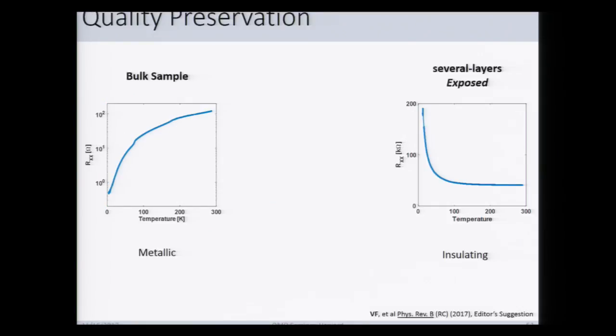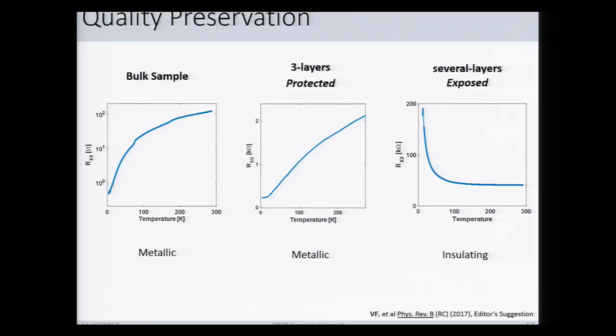The first point is let me first review what happens with bulk samples and exposed samples. Here's a sample we measured in our own lab in a semi-log scale. The resistance is a function of temperature, and we see this nice metallic temperature dependence, where the resistance drops by a couple orders of magnitude. If we take a several layer thick sample that's exposed to air and lower the temperature, we see it rises up, and that's indicative of degraded behavior. And if we take a 3-layer sample that's been fabricated in the scheme I just described, we see that the resistance does drop nicely with temperature by about an order of magnitude, indicating a nice metallic state. So that's a good start.